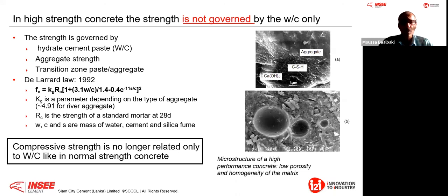And there is one important factor, the transition zone, because as I said, between the paste and the aggregate. Therefore, if you can improve it, you improve the bond, the wall effect. By improving the bond, you increase all the engineering properties. And when I say engineering properties, I'm not meaning only compressive strength. That is how we build bridges that last for 100 years, 120 years.